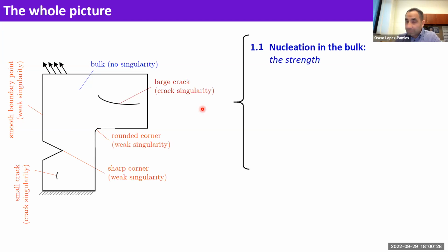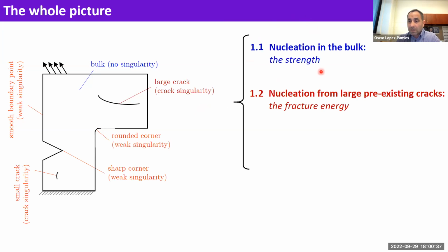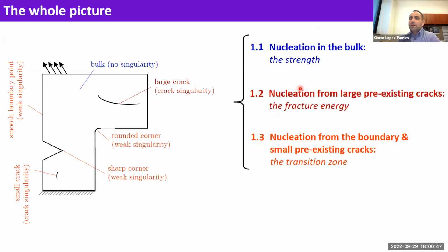So the bottom line is the following. What we know now from experiments is that nucleation in the bulk is controlled by the strength of the material. Nucleation from large pre-existing cracks is controlled by the fracture energy, or if you like, Griffith, right? These are the things that I showed you before. These are just experimental observations. And then anything in between really is a transition zone. It's like there is a mediation between these two limits.